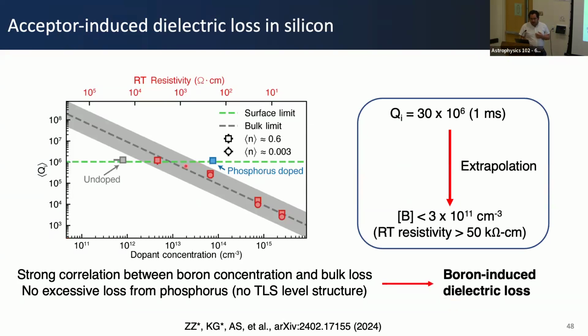Okay, so this is nice basic science, but this is something that's relevant. If you've ever bought a silicon wafer, the thing you look for is resistivity to give you a proxy for how pure it is. So oftentimes you can buy wafers at a few 10,000 ohm centimeter. And what this tells us is that if our extrapolation is correct, this actually puts a limit on the Qs you can get at the 10 to the 7 level. So there are some error bars here, but this is a serious limitation for the maximum Qs that you can achieve, the maximum loss energy.